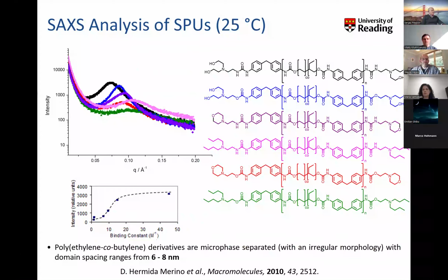Now, we're pretty confident that we have phase separation occurring as a consequence of some SAXS analysis that we did, where we see irregular morphologies with quite broad SAXS peaks, indicating domain spacings ranging between 6 to 8 nanometers. And what was interesting was that we were able to correlate the intensity of those Q bands with the hydrogen bonding strength of the end groups, where the most strongly associating end groups have the most intense Q bands.